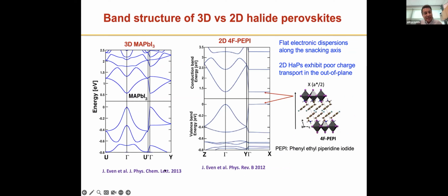If you look at the electronic structure, on the left, I'm showing you the band structure of a 3D perovskite, and you can see that this is a direct band gap semiconductor where the minima of the valence band and the conduction band meet at the gamma point. And it has got nice dispersion. And so this has low effective masses, pretty good transport properties, good mobilities in this material.